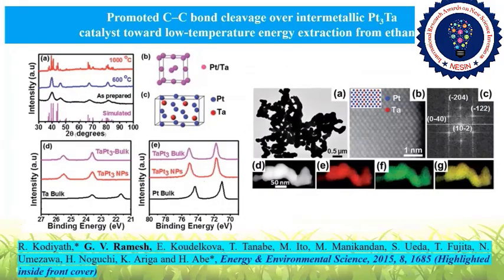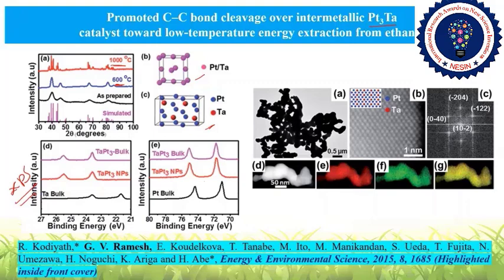In the same way, we synthesized Pt₃Ta nanoparticles using platinum and tantalum precursors in dry diglyme with superhydride as the reducing agent. After washing and annealing up to 600°C and 1000°C, the 1000°C sample shows a perfect intermetallic structure of Pt₃Ta. This is further confirmed by HAXPES data and TEM microscopic studies showing the ordered structure of platinum and tantalum with exactly matching FFT. EDX confirms platinum and tantalum are uniformly distributed throughout the particles, confirming formation of Pt₃Ta intermetallic nanoparticles.